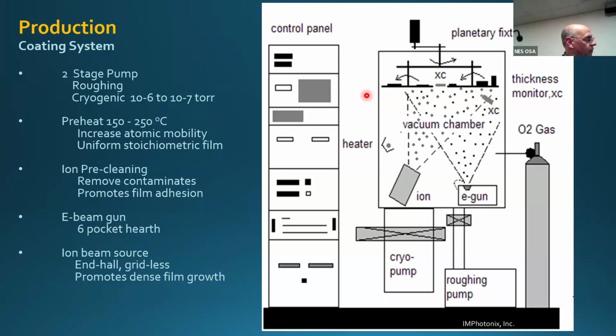And as the film is growing, the argon ions are breaking down the columnar growth that you would get with the film growth. It pretty much makes it a denser coating. You can get higher indexes. So we use ion beam technology to assist our deposition.